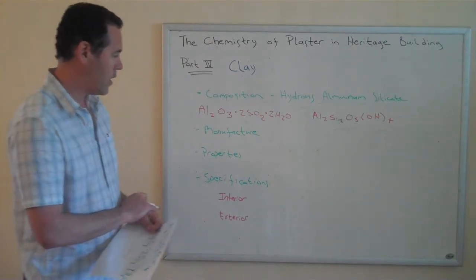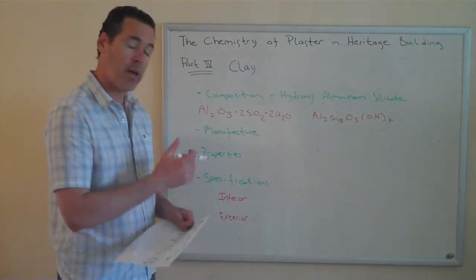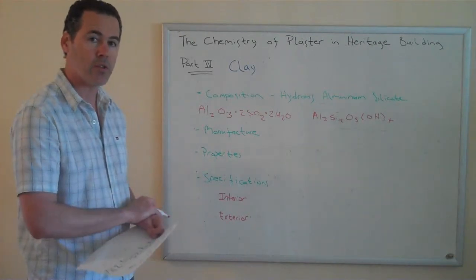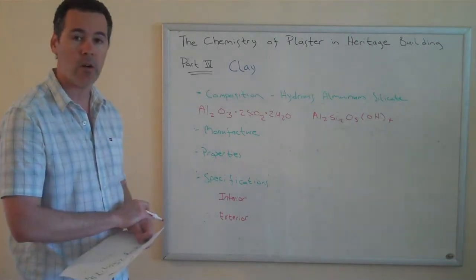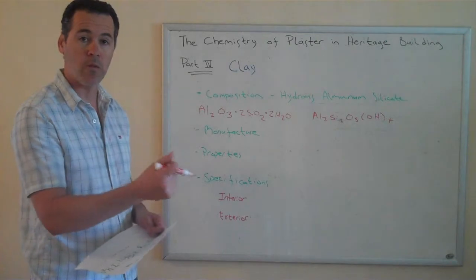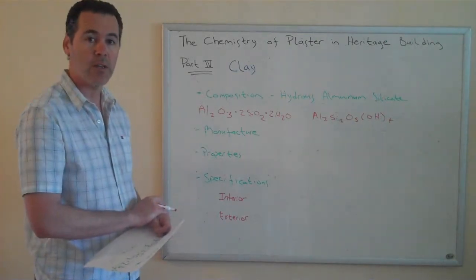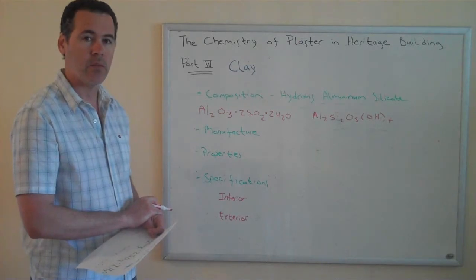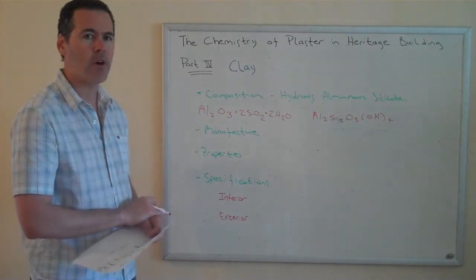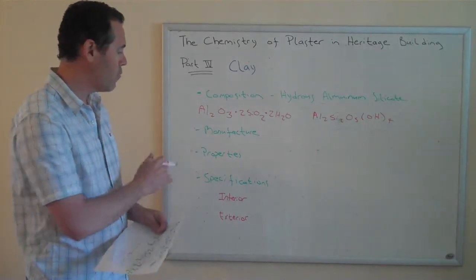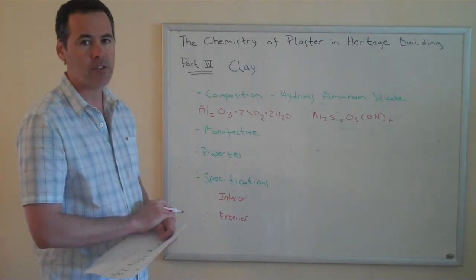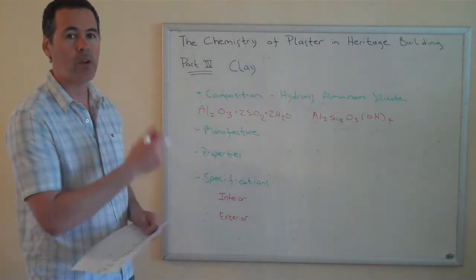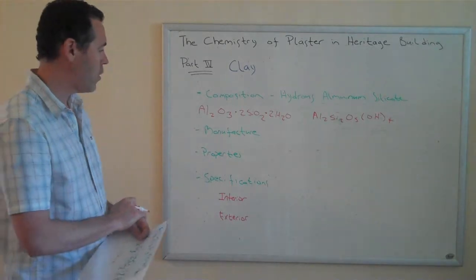Clay has certain properties. Since it doesn't have this baking process, it doesn't have a chemical set. It has what we refer to as a mechanical one. You add a little bit of water, you spread on the plaster, and then it simply dries out. With that water leaving the system, it becomes a little bit friable, though very soft. So it's very important in the application of clay plasters to compress it, perhaps with a trowel or a wood float.